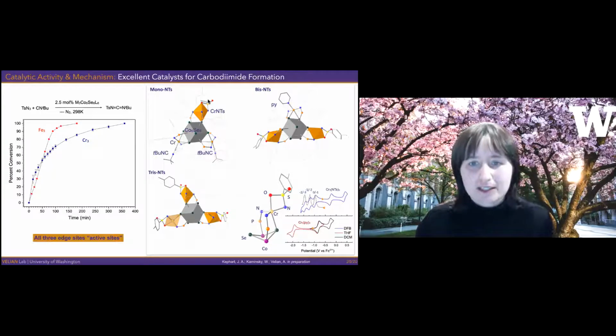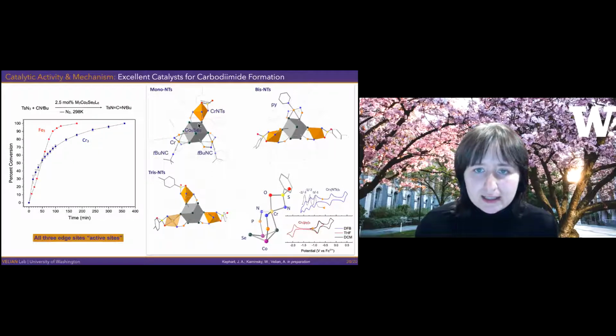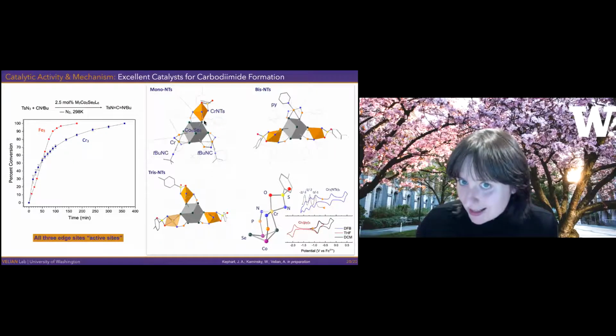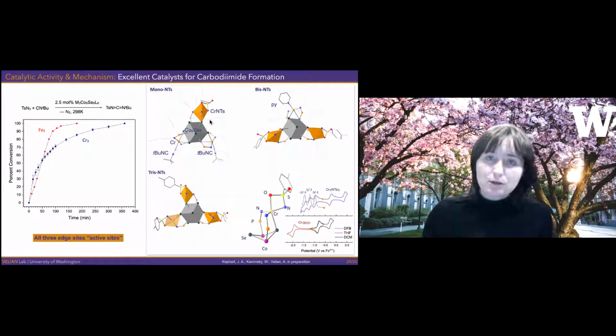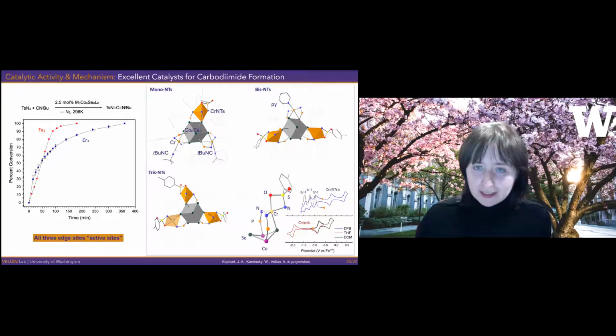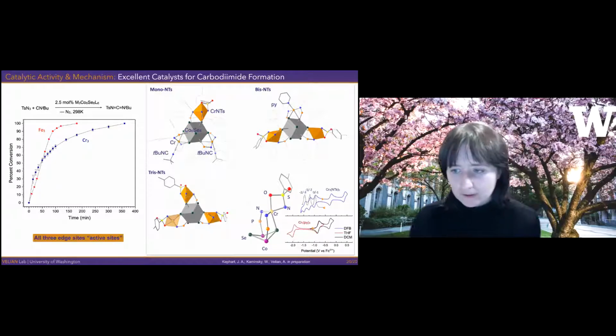And so here's an instance where a single edge site is binding to this nitrene, which is essentially our catalytically competent intermediate to then react with isocyanide and form carbodiimide. And then at 2 sites, and then at 3 sites. And that's just showing the connectivity here of this nitrene bound to the chromium surface. And so I want to make sure I'm staying within time here.